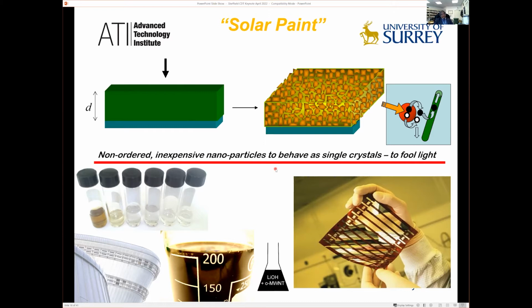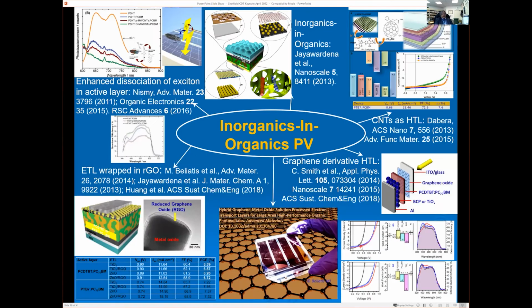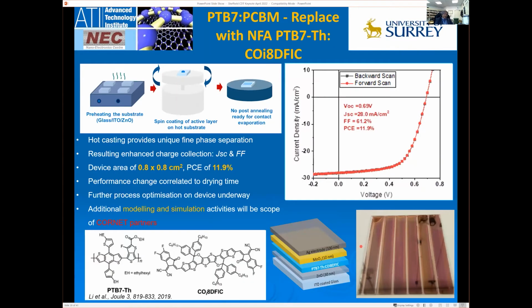polymer solar cells. Now, you immediately note that I've gone from 300 microns to 100 nanometers. There is 1,000th of the material used when we start using nanomaterials that can have equal or more absorbability associated with these structures. So the idea here is that we will make this into ink and then it will be printable. Now, we've done quite a lot of work on this, as have many other groups within the UK. We are working at pretty decent power conversion efficiencies at present when we come to scaling materials and working up.